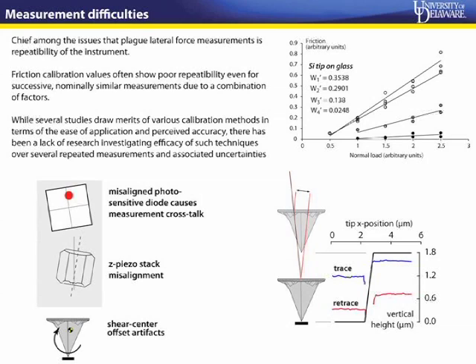One of the other things about an AFM is it is really susceptible to changes in the output you get just based on the state of the system. This is one of the things that has again been pointed out by a few authors. If you think about the piezo, if the tip moves up and down in AFMs where the laser position does not change, or what are called standby probe AFM systems, you notice that even if you change the Z height of the piezo, you're essentially shifting the position of the laser which is incident on the photodetector. So if you think about a measurement that you perform today, and tomorrow your Z piezo position is different, you're essentially going to end up with different numbers. And that's one of the key things with lateral force measurement calibration methods.